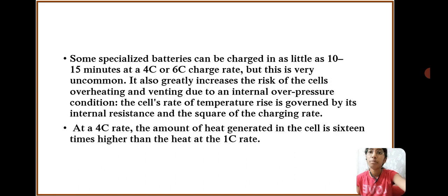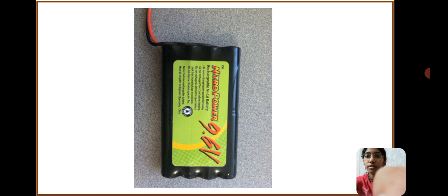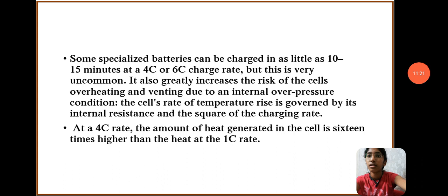Some special batteries can be charged in as little as 10 to 15 minutes at a 4C or 6C charge rate, but this is very uncommon. It also greatly increases the risk of cells overheating and venting due to internal overpressure. The cell's rate of temperature rise is governed by its internal resistance and the square of the charging rate. At a 4C rate, the amount of heat generated in the cell is 16 times higher than at a 1C rate.